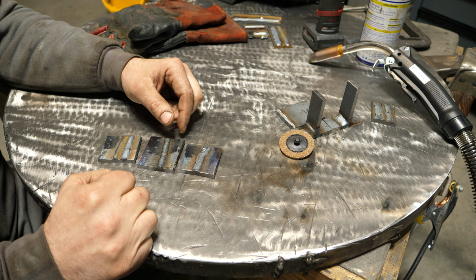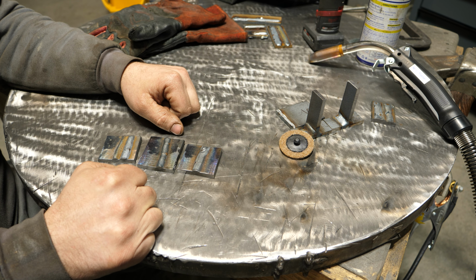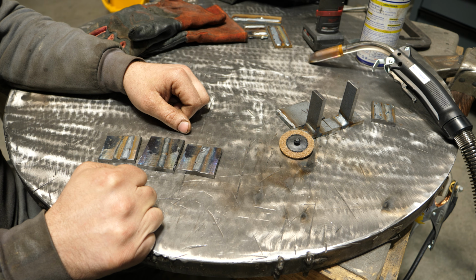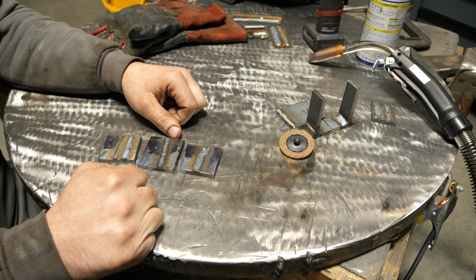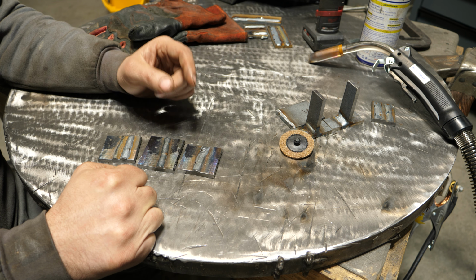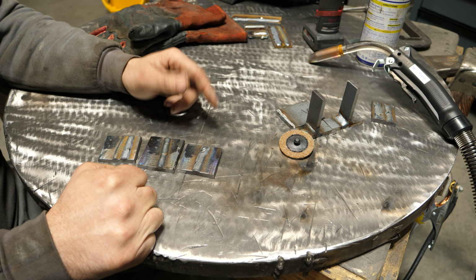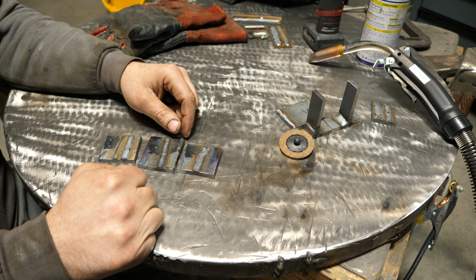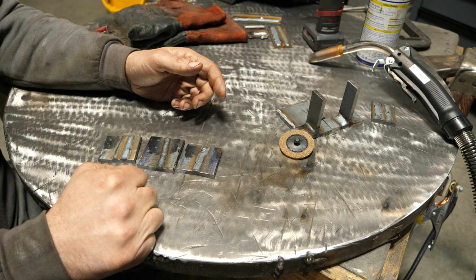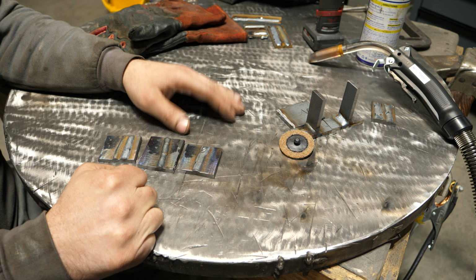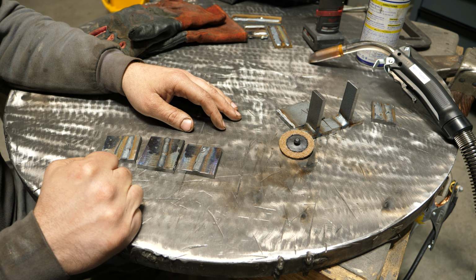This is quarter inch. This is ideal for spray, quarter inch and up. If you've got a bunch of eighth inch material to be running, you don't want to be using spray. You'll burn right through. Not to mention, if you have out of position welding, you're probably not going to want to use spray unless your machine does pulse. And again, you're welding on thick material. So there's pluses and minuses to every welding process.